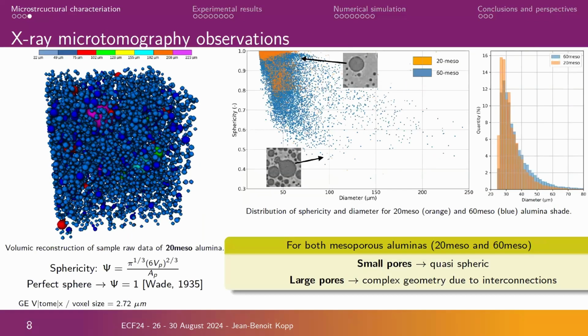Okay, so we have, of course, studied the microstructure in 3D with X-ray microtomography. We have a good evaluation of the microstructure with statistical evaluation. An example here for 20 meso and 60 meso: we have small pores with very spherical geometry, and sometimes we have some interconnection due to the polymer preforms in the mixture. So that is why we have some large pores in the microstructure, due to the interconnection.